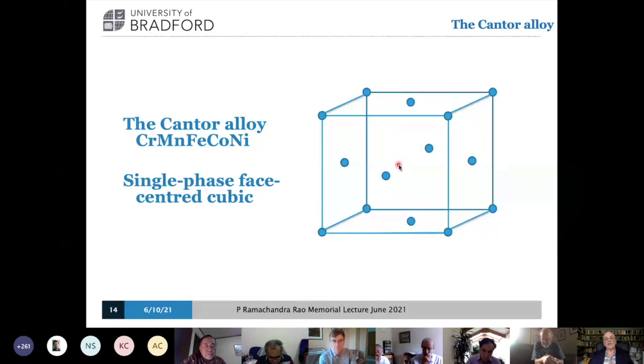Now, nobody would have predicted this material would be a single phase, face-centered cubic material. What does it mean? It means that in this case, 20%, all of the atoms have the single structure here. There's no compound formed. And 20% of these atoms at random are chromium, manganese, iron, cobalt, and nickel. Very recently, it's been demonstrated and shown they are almost completely, absolutely random. There is no what's called short-range ordering. And so they really are very randomly distributed. It's what's called an ideal solution, very close to being that.